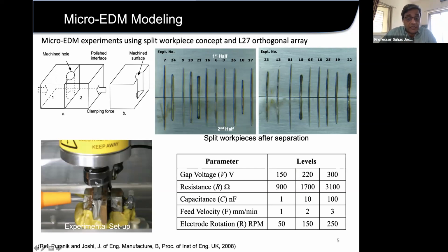So you can see here, these are the two surfaces, and this is a very small electrode, about 400 micrometers, and we actually machine at the interface of the two surfaces so that you can open the two surfaces and see how the holes are actually machined. So that is what you can see, these are the surfaces opened like this. So the holes are made like this, and the surfaces are opened and kept like this. So this is the top half of the hole, and this is the lower half.